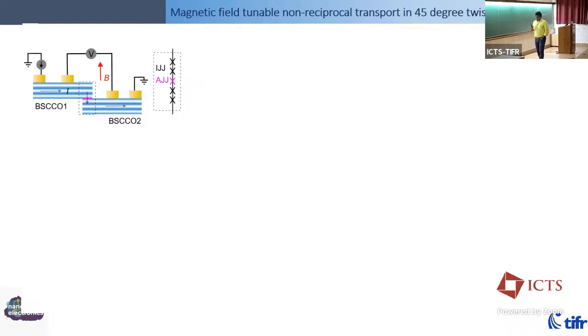When we peel it off and put it back, we can put it back with an accuracy of about, for this stacking setup inside the glove box, 0.3 or 0.4 degrees. So they show small asymmetry, but they do show asymmetry. Not as much as the 45-degree twisted device.